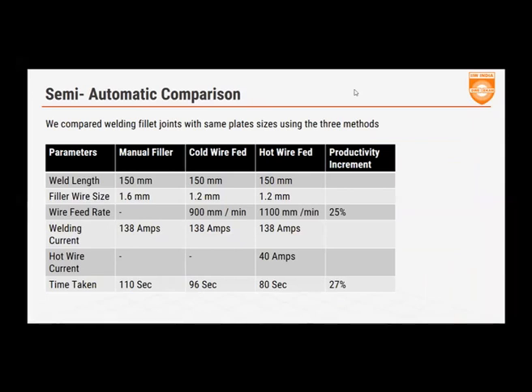All right, so if we were to look at how much productivity improvement is expected from a manual intervention or using these tools, you can see a small experiment on about a 150 millimeter length fillet joint. When welded directly by the welder using a 1.6 mm filler wire and the present current at 138 amps, he could complete the joint in about 110 seconds.